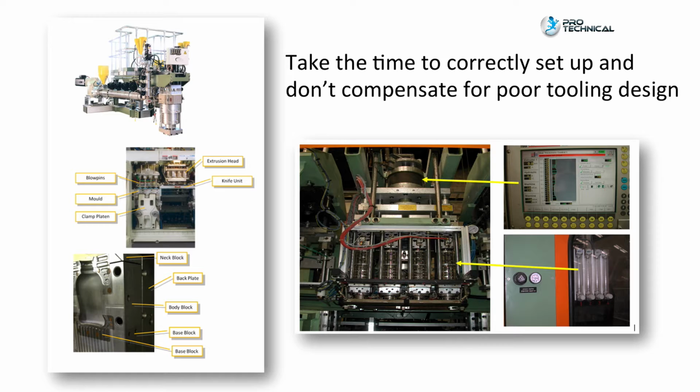Faulty gauges. Well, they speak for themselves. They will destroy your results and should be replaced on a regular basis. Incorrectly set positions like the extruder position. If this is off-center by only a few millimeters, then it will give the appearance that the parison support air needs to be tweaked, or the parison needs to be adjusted. Record the extruder position very, very accurately.